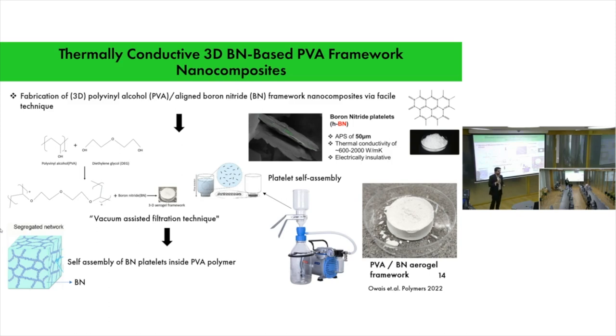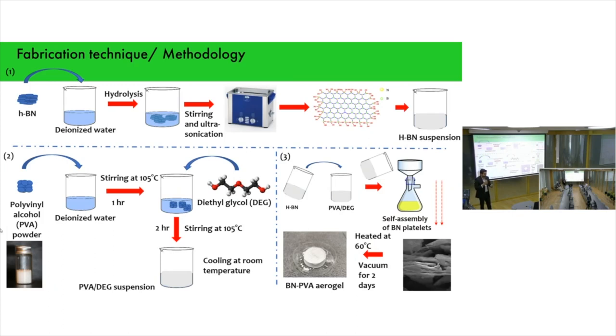By using this vacuum assisted filtration technique, here you can see, I self-assemble the platelets with the use of a pressure gradient. By applying the pressure gradient, the liquid is sucked down through the process, and the boron nitride platelets are self-assembled by pi-pi attraction. Then you have this self-assembled boron nitride PVA polymer with a segregated network. So this is the fabrication technique. Initially, I surface modified boron nitride by hydrolysis to induce some hydroxyl groups on the edges of boron nitride. Similarly, PVA polymer was synthesized, and then added drop-wise into the vacuum assisted filtration system. So then we have this BN PVA aerogel.